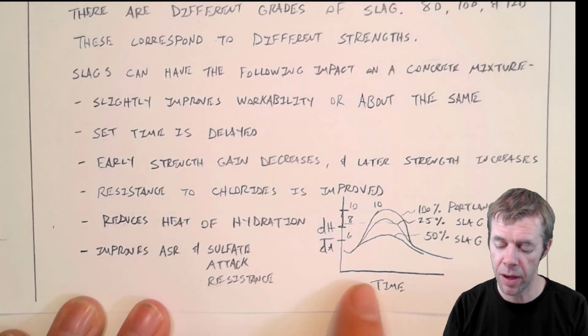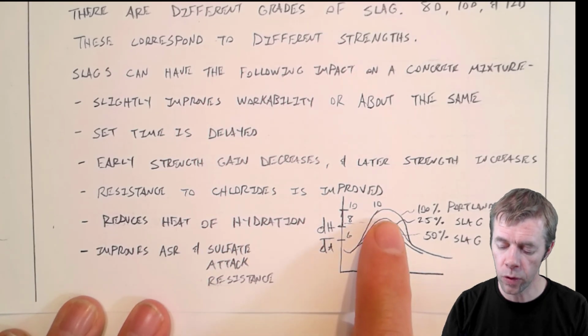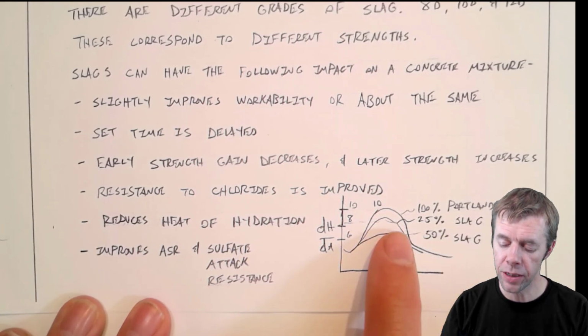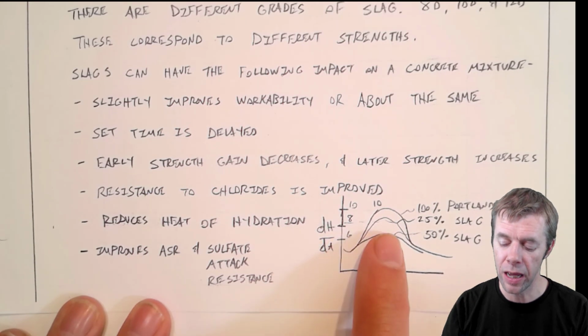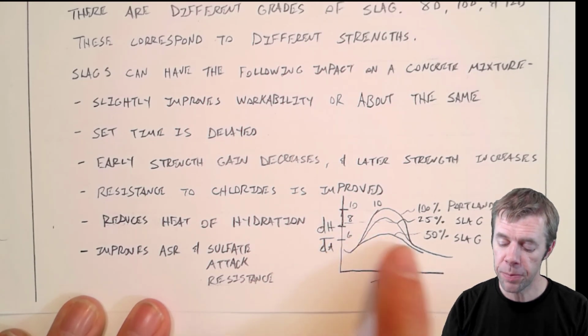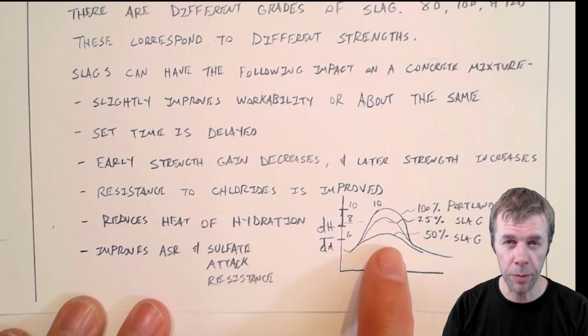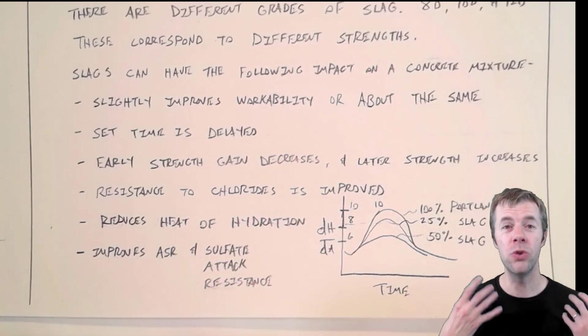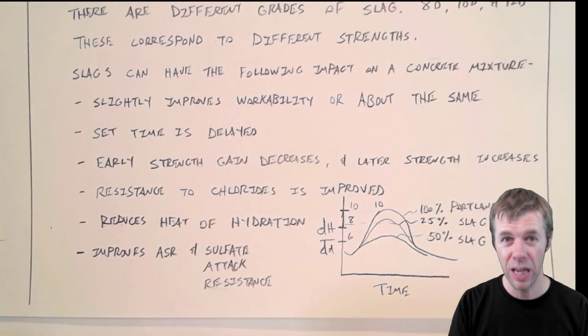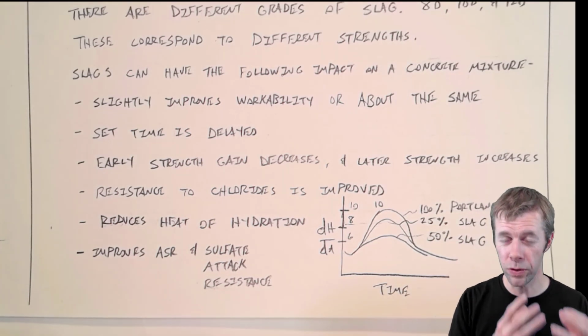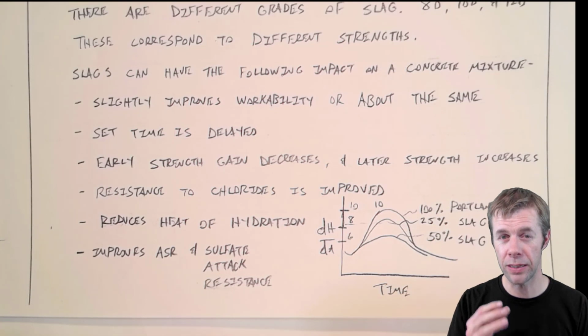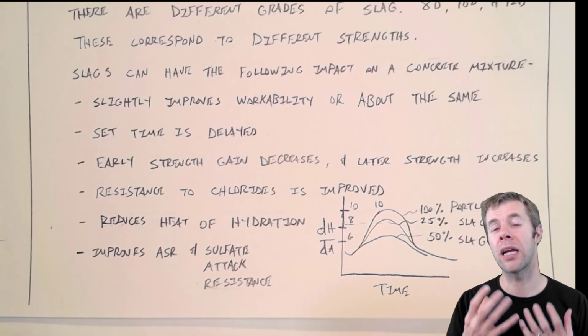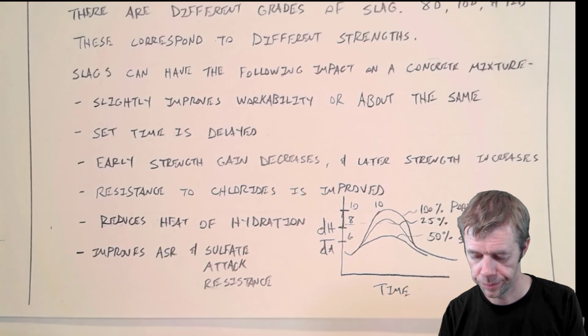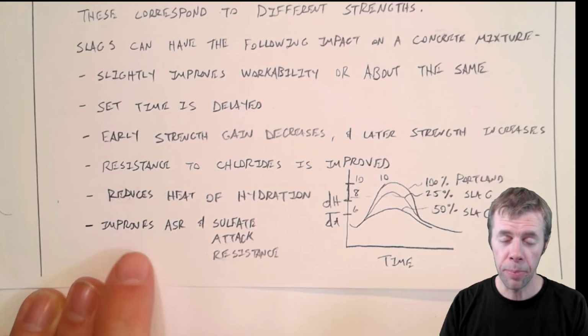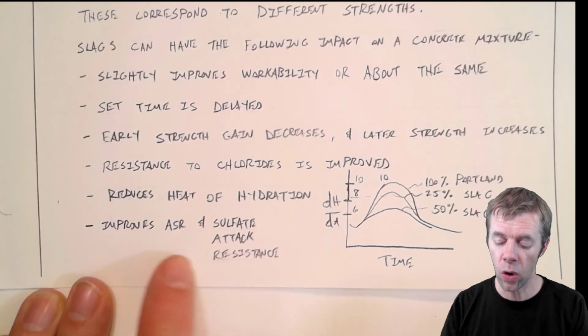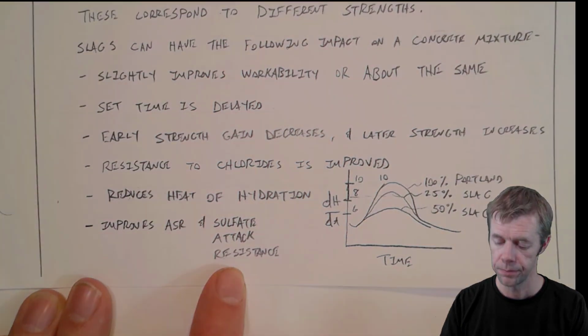This is time and this is the amount of heat given off. And here's 100% Portland cement. Using 25% slag, it's reduced my heat given off by about 20%. 50% slag reduced it by about 40%. So again, it's reducing the amount of early age heat given off because there's not as much Portland cement reacting early on. And that slag's gonna react later, but it's not gonna have as much exothermic reaction. It's gonna improve performance in alkali silica reaction and also resistance to sulfate attack.